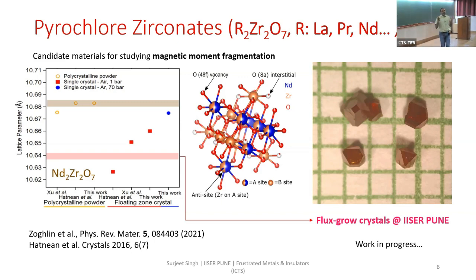compounds, the exchange is to begin with very weak. On top of it, it is highly frustrated. So these materials are very sensitive to structural modifications, structural changes, which could be because of off-stoichiometry or because of real structural changes. So here what happens is that when you grow these materials, and in fact, the crystal